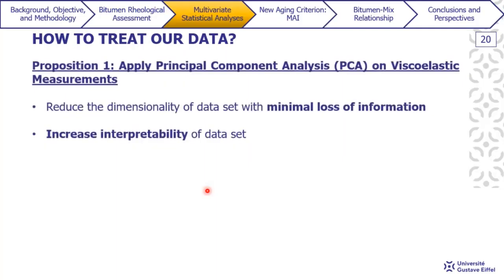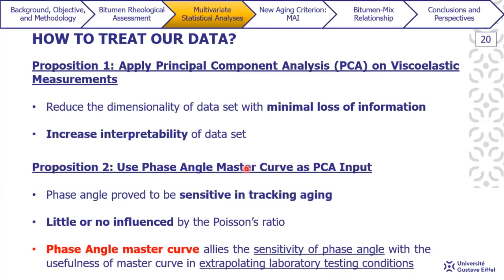In this case, we have principal component analysis, or PCA, that has long been used in several science fields, including bitumen-related works, to reduce the dimensionality of our data set with minimal loss of information, which helps increase interpretability of our data set. Since, as I just mentioned on the previous slide, the variation of the phase angle takes place in a very large range of reduced frequency, which would represent hundreds of columns if you represent the data point by point to describe a curve, PCA was used to select the most relevant information that could be more representative of the whole curve.